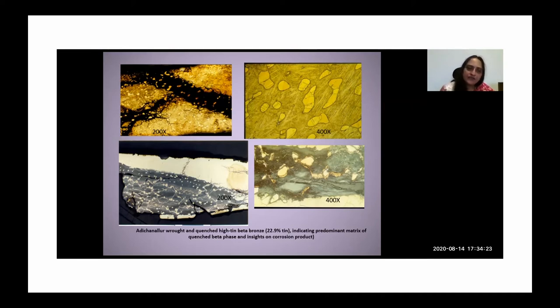And just to give an idea of what has been happening with the alpha islands, when you look at them in higher magnification, you see that the alpha islands have not been corroded out, but around them you see this coppery color, because what has happened is what we call redeposited copper. This redeposited copper is a corrosion product, and to some extent it is also an indication of the antiquity of objects. For instance, if you looked at more recent objects, you would probably not find this kind of redeposited copper. That happens only over a long period of time.